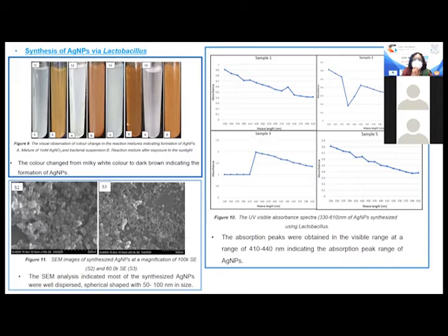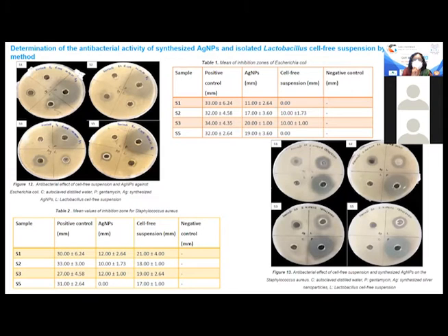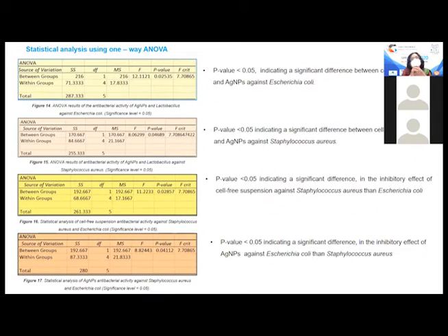So these are my well diffusion plates to determine the antibacterial activity. This is against E. coli, and this is against S. aureus. And here are the statistical analysis values. The p-value is in figure 14. The p-value is less than 0.05, indicating a significant difference between cell-free suspension and silver nanoparticles against E. coli. And figure 15 shows you a p-value less than 0.05.